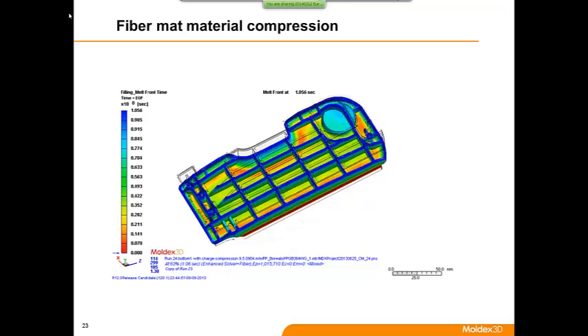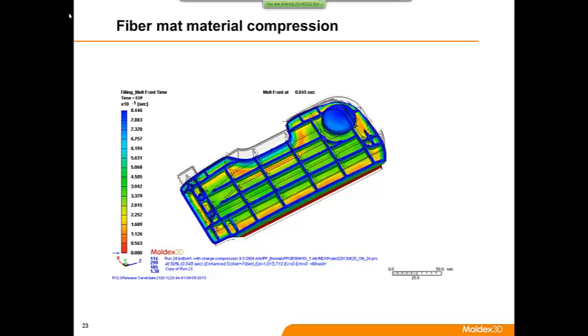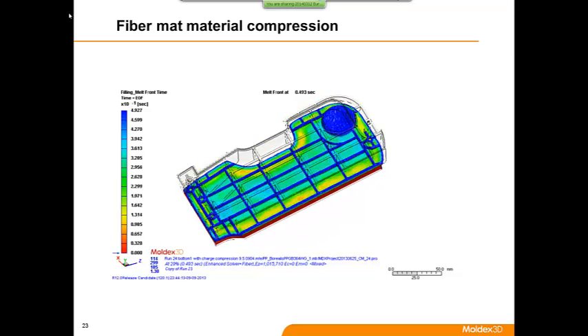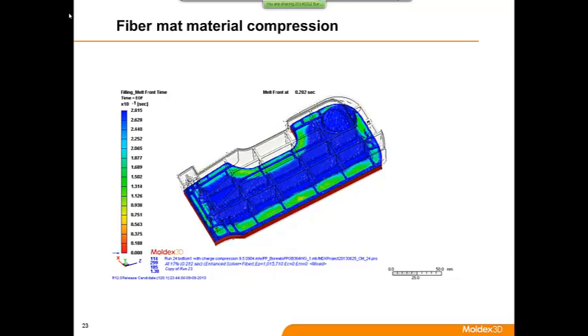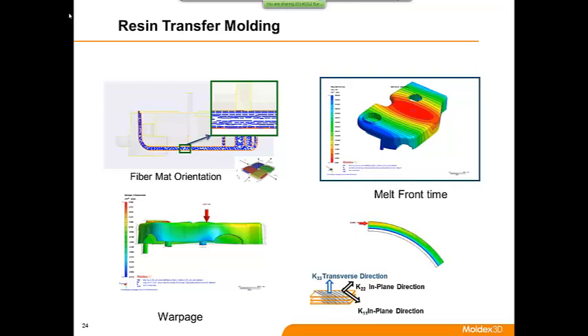And this is one of the examples showing a glass mat thermoplastic material is pressed into the mold. So you can see it's not like your traditional injection molding process. Everything is compressed from the other side, and you can see how does it goes into those rib regions. And we also have the RTM module. So we can use other softwares as the pre-processing tool and import the fiber mat orientation, or you can define the fiber mat orientation inside our software, and we can evaluate the melt front, and you can see animation on the bottom right corner. Because there's a guide film on the top, so it flows faster on the top, then gradually sinks down through the Z direction. Because in this case, the Z direction has a lower permeability.